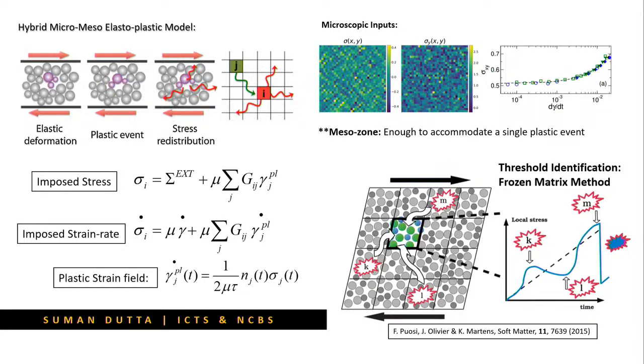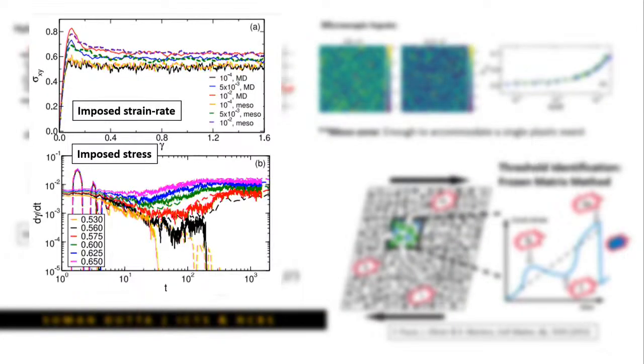We feed all these things into the elastoplastic model, and then we make some predictions about the onset of flow for different levels of glass, and we compare it with the microscopic simulation to verify whether the predictions are robust or not, and whether this prediction holds for all different classes of glass or not. So, this is what we obtain, that for different values of the imposed strain rate and the imposed stress, the elastoplastic predictions are quite robust.